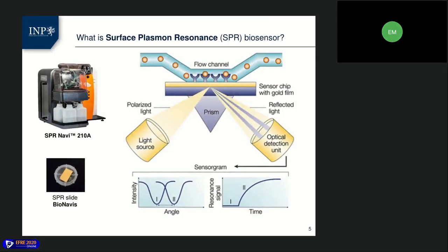Surface plasmon resonance is an optical technique which measures refractive index changes in the vicinity of thin metal layers in response to biomolecular interactions. The light passes through a prism, reflects off the back side of a sensor chip surface and goes into the detector. At a certain incident angle, light is absorbed by electrons in the metal film of the sensor chip, causing them to resonate. These electrons are surface plasmons, which are sensitive to the surrounding environment. The result is an instant intensity loss in the reflected beam, which appears as a dark band and can be seen as a dip in the SPR reflection intensity curve.